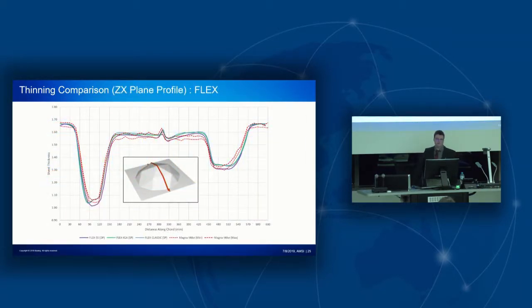All right, and this is my last slide. So here we used a second method now to explore the thinning. We used a device called a Magna-Mike, which is produced by Olympus, I think. There's a sort of ball bearing and a probe, and as the probe comes closer to the ball bearing, it uses the Hall effect to determine the precise gap between the ball bearing and the probe. So as long as your part isn't ferromagnetic, which this aluminium part wasn't, we're able to roll it over and actually take measurements across that profile.